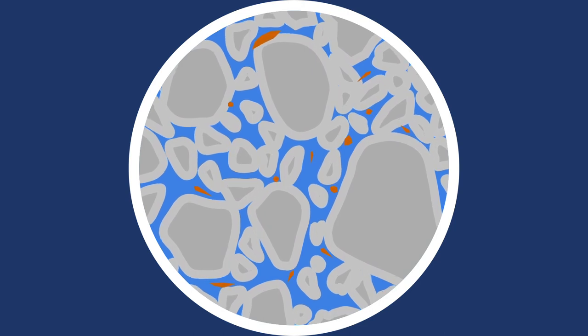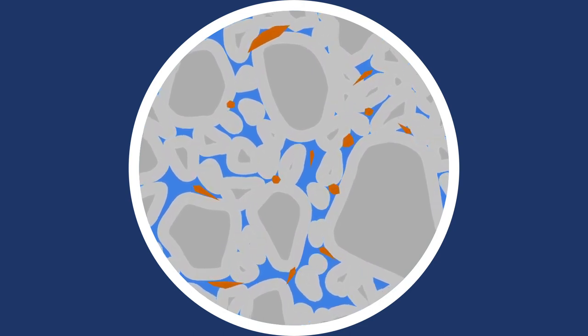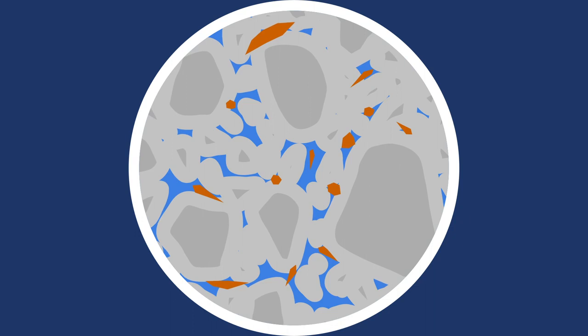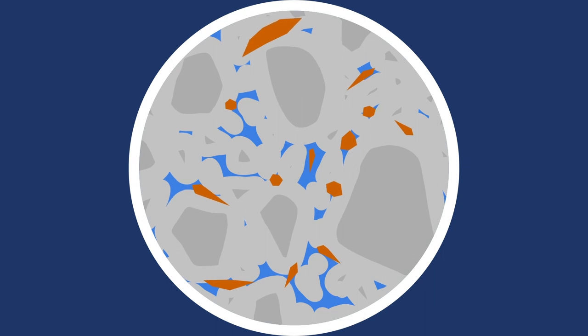As hydration proceeds, hydrates fill up the microstructure, reducing porosity. This increases both strength and durability. These hydrates form both in between grains and on their surfaces. In one way or another, this accumulation of hydrates reduces the space and ease at which hydration may proceed, which, along with the diminishing reserve of anhydrous phases, contributes to the slowing down of the hydration rates.